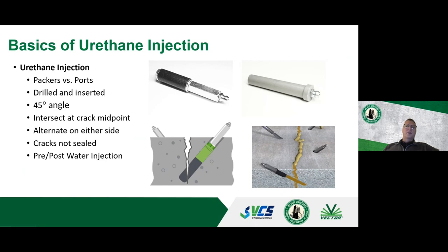And so you're going to drill down at a 45-degree angle. You're going to be X number of inches away from the crack based on the thickness of the crack. And then you're going to be able to install that packer there to get the urethane into that crack.